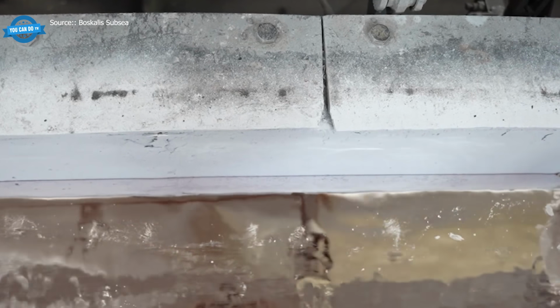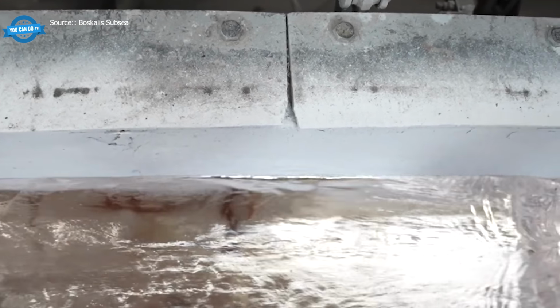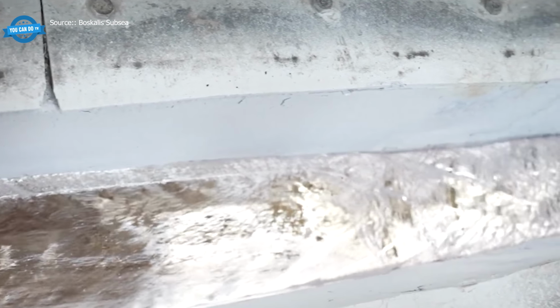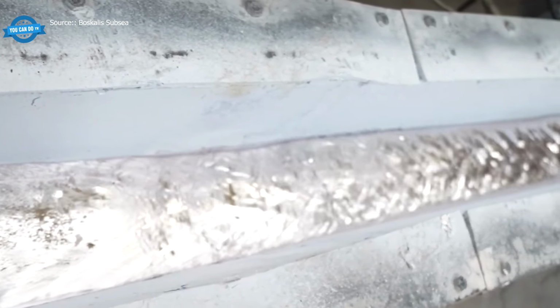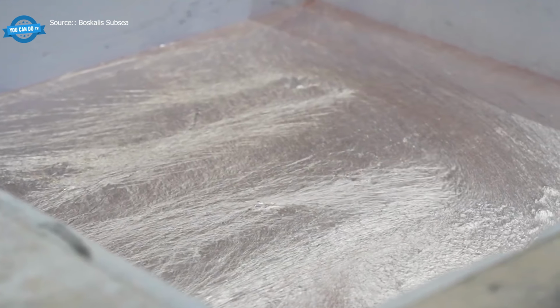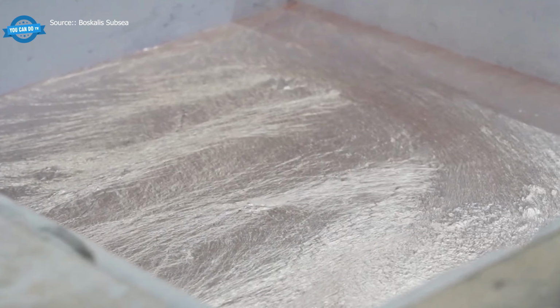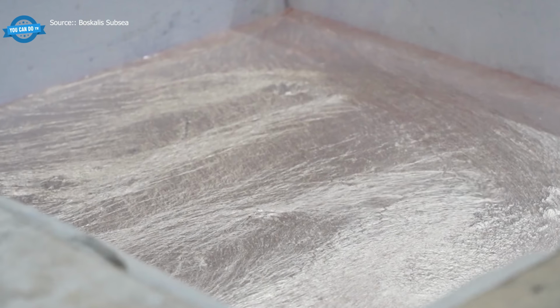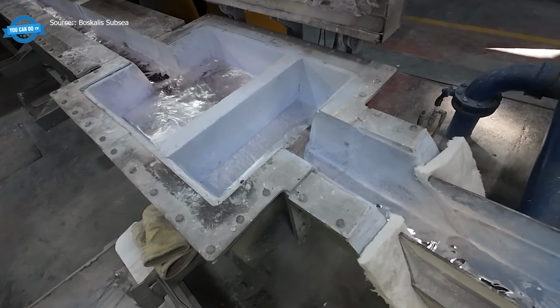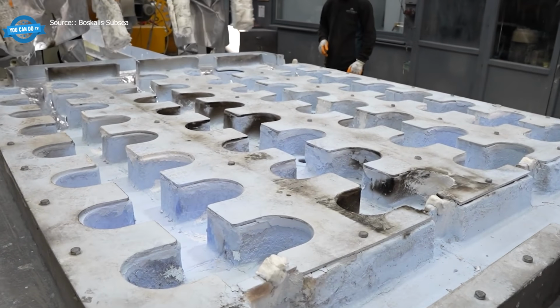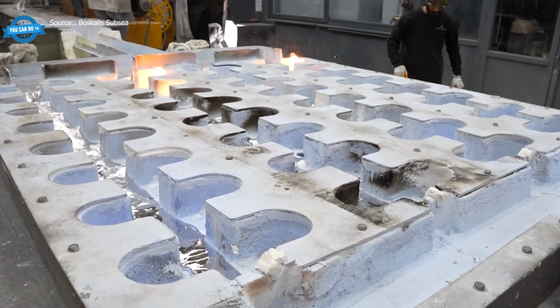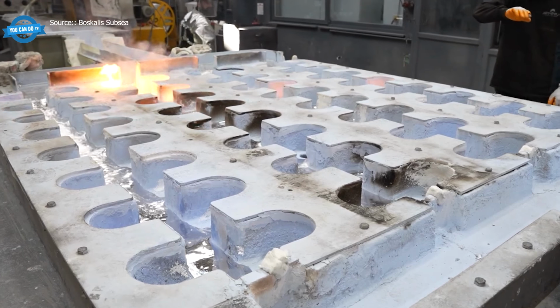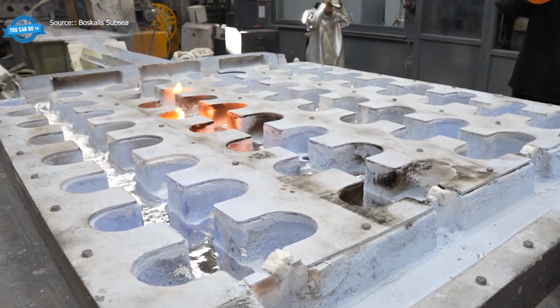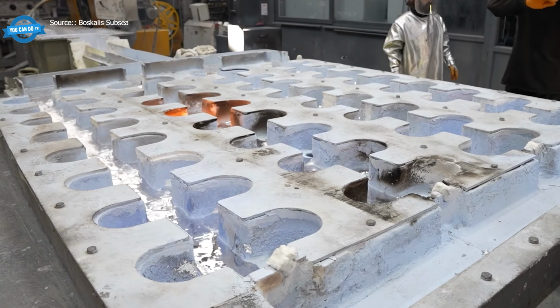Producing them at industrial scale requires a specific casting method, direct chill casting, where molten aluminum flows continuously into a water-cooled mold and gets pulled downward as it solidifies. The mold shapes the diameter, the water cooling controls the solidification, and the length depends on how long the operator runs the pour. Each billet has to be free of internal cracks, cold shuts, and porosity, because every defect in the billet becomes a defect in whatever extrusion or rolled product comes next.